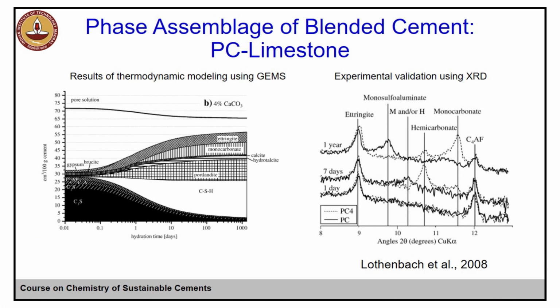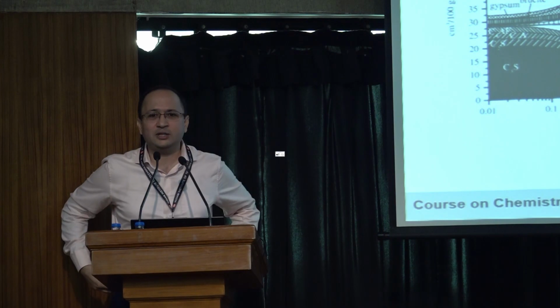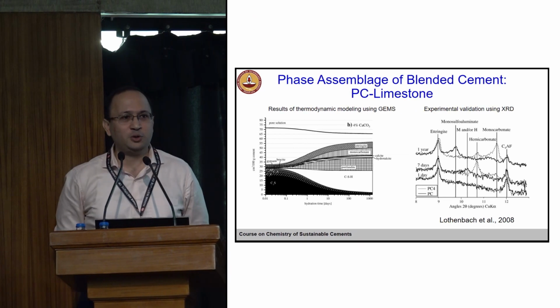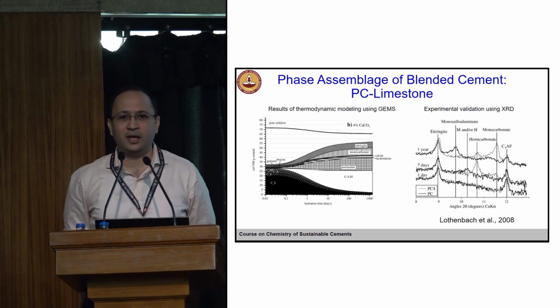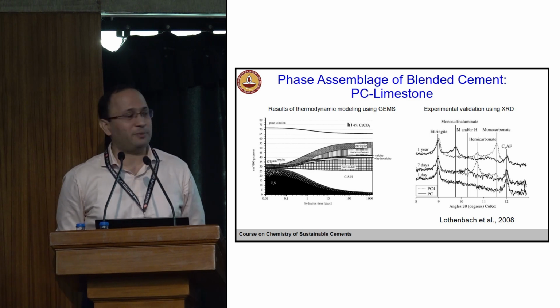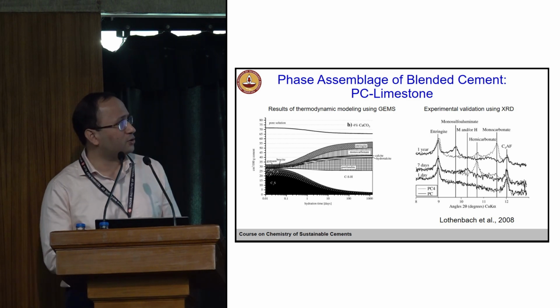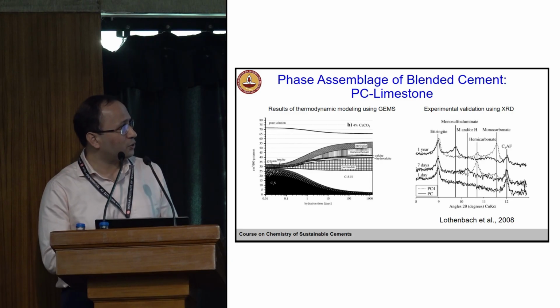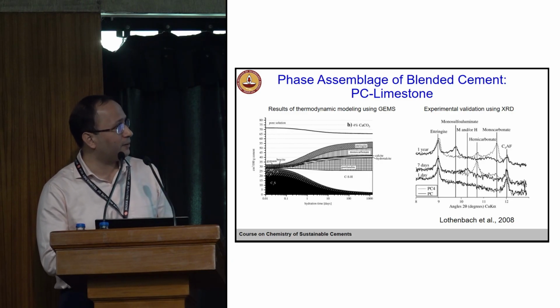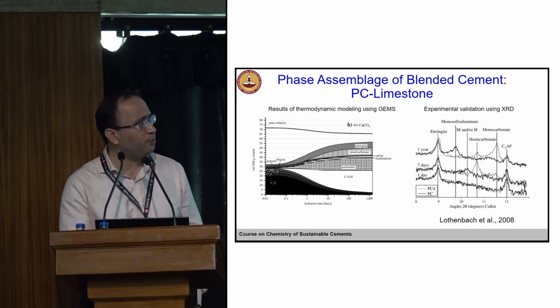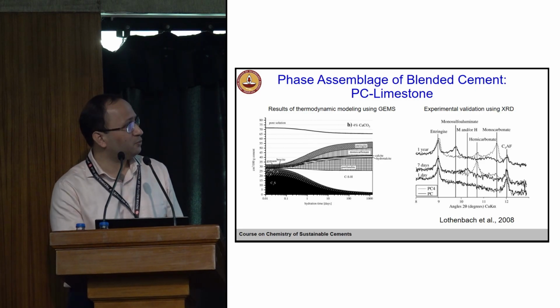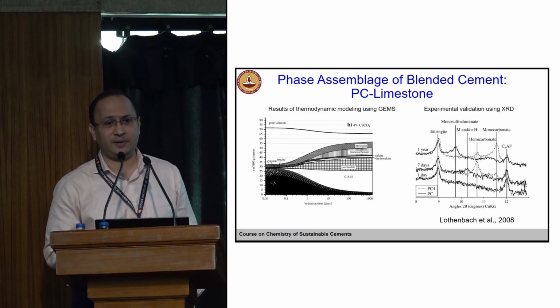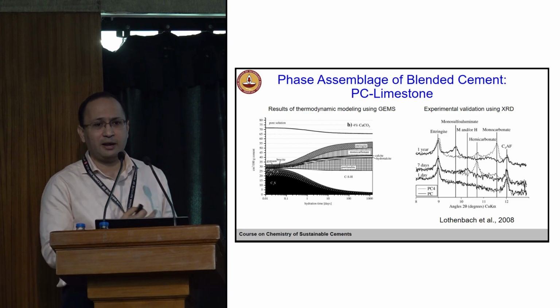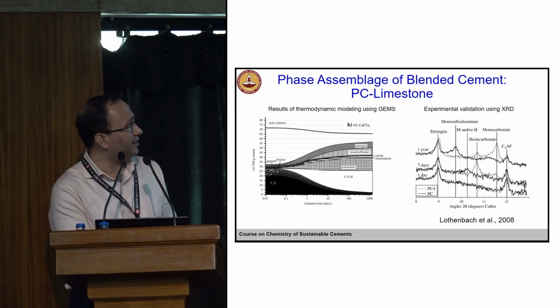So limestone is an interesting material. We'll see its synergy with calcined clay later. But first, if you just use limestone, in the US for example, PLC is very popular. Like in India we use PCC, PPC. So in the US, PLC, Portland Limestone Cement. So just adding limestone can also bring about a lot of changes. So you see here phases like hemicarbonate or hemicarboaluminate, monocarbonate kind of phases, which can be detected using X-ray diffraction. If you are familiar with X-ray diffraction, it can help you detect these phases. And the chemistry also changes.